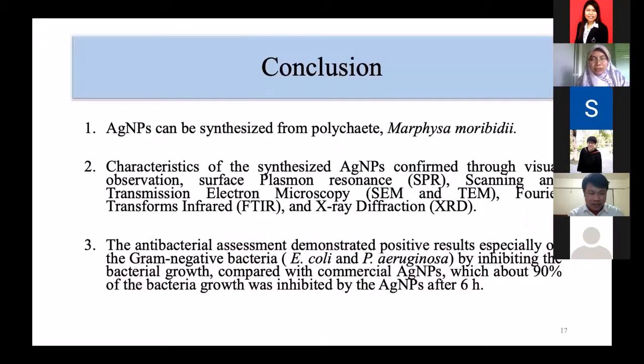So as conclusion, we confirm that we can synthesize silver nanoparticle from the polychaete, and we managed to characterize and also validate the silver nanoparticle formation using several methods. And through the antibacterial assessment, we also confirm that our synthesized silver nanoparticle can inhibit the bacteria, especially from gram-negative bacteria, E. coli and P. aeruginosa. It was at 6 hours. It was about 90% and up to 100% when we tested after 24 hours.